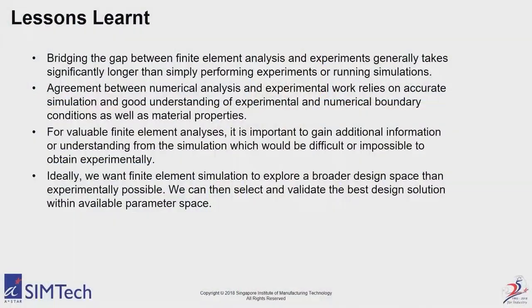Now, the lessons learned, or still in the learning process, is that bridging this gap between finite element analysis and experiments takes a very long time. It takes much longer than just doing the experiments and much longer than just doing the simulations. So these nice agreements that you see here, and there's actually no fudging of data here, come from going back to do the experiment, going back to adjust boundary conditions in the simulation, going back to try and change boundary conditions in the experiment because we know there's a bit of movement which is decreasing our stiffness that is not present in the FE model. That's what takes time and often creates a lot of frustration that just needs to